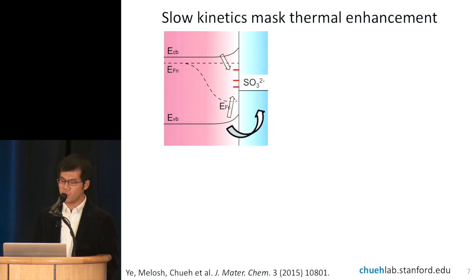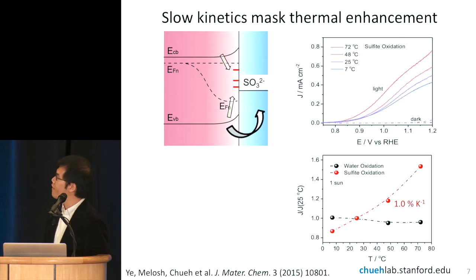So to remove this effect, this was actually a suggestion from Nate a number of years ago, we just look at a fast redox couple, replacing the water redox couple with a sulfite couple. This is a very quick redox couple that allows you to extract the carrier. It's as if you have a perfect catalyst on the surface without having to have one. And the results were very encouraging.